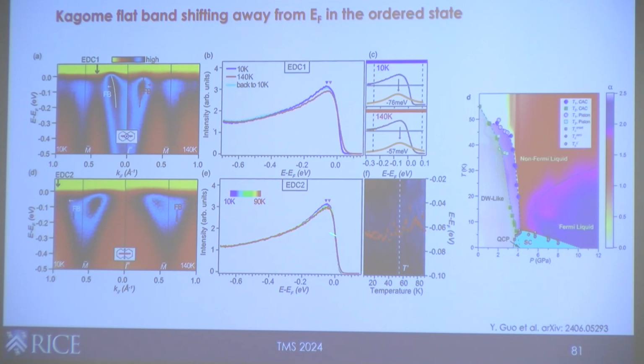And we can track that this is roughly, give or take, something that onsets at least largely consistent with the ordering temperature, right? So it suggests that this flat band is at least responding to, if not responsible for, the density wave orders here. And one may speculate, what is the effect of pressure?